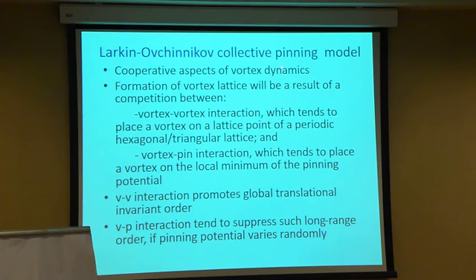The second one is the Larkin-Ovchinnikov collective pinning model, in which they deal with cooperative aspects of vortex dynamics. In their model, the formation of the vortex lattice is a result of competition between vortex-vortex interaction, which tends to place vortices on the lattice points of a periodic hexagonal or triangular lattice, and vortex-pin interaction, which tends to place a vortex on a local minimum of the pinning potential. So what does it mean? It means that vortex-vortex interaction promotes global translationally invariant order, while vortex-pin interaction tends to suppress such long-range order if the pinning potential varies randomly.